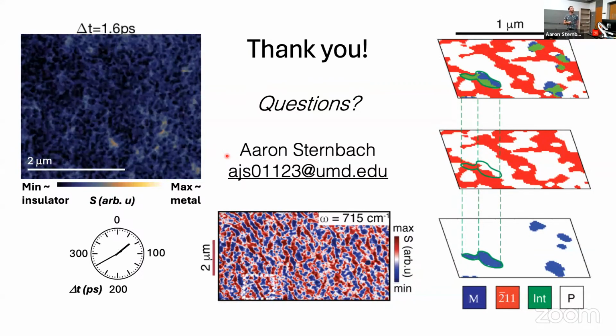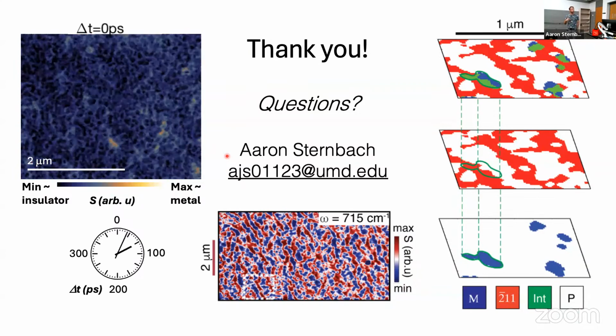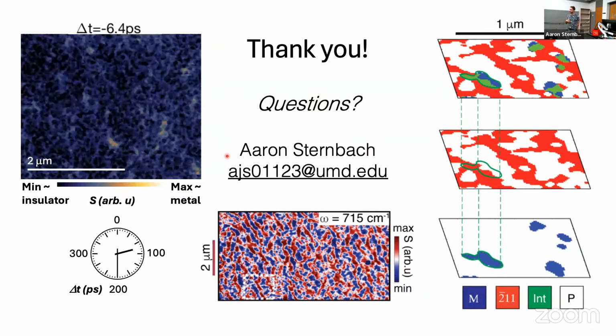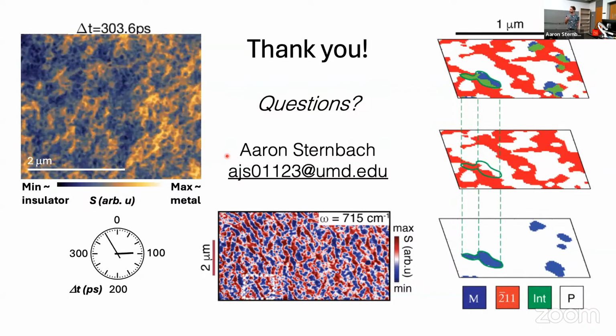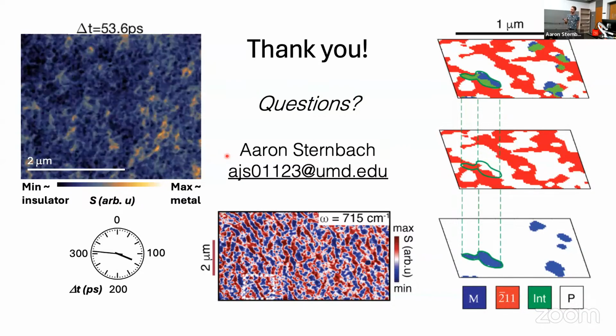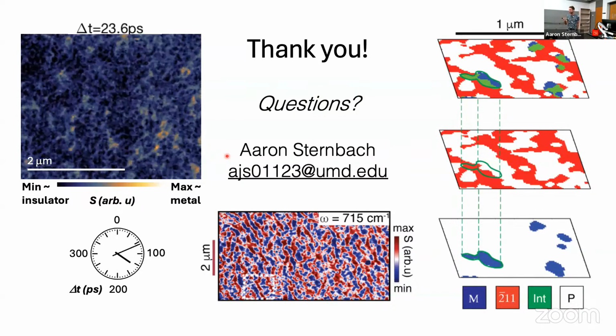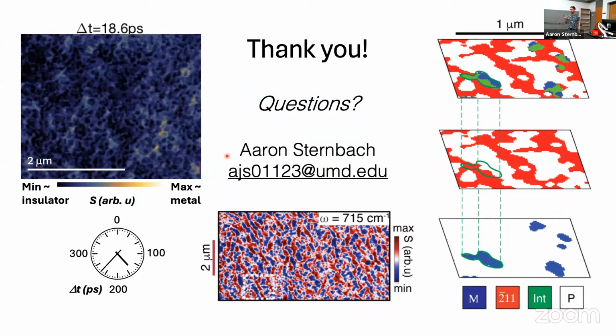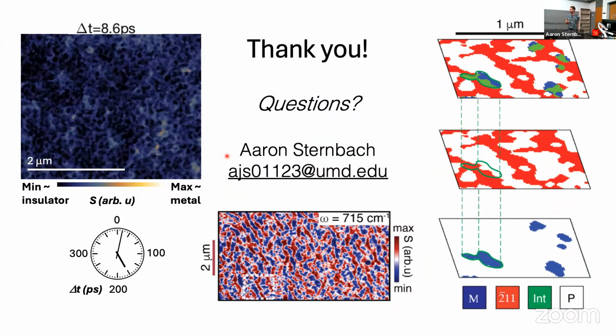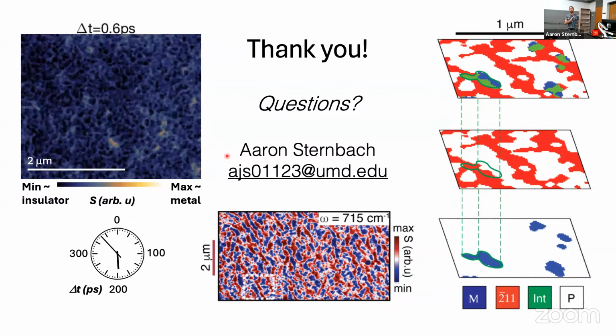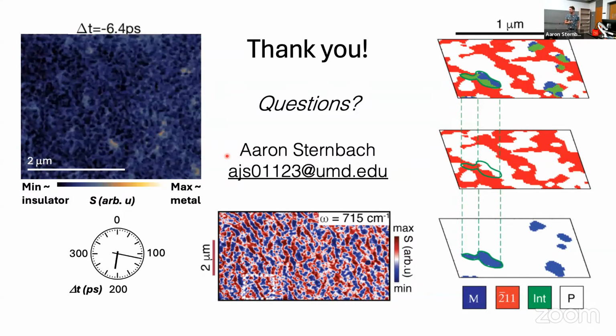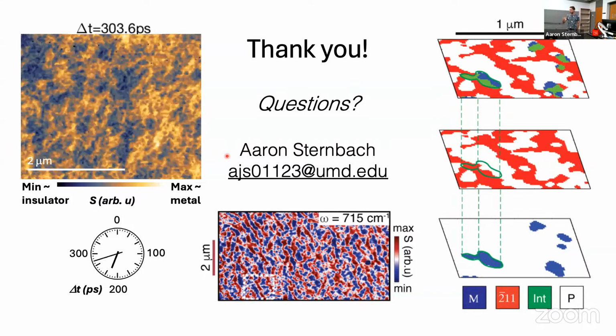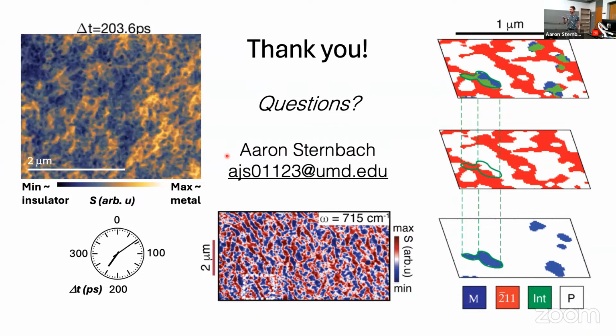And there's varying degrees of support for the notion that you can produce the electronic transition, but just at the beginning and just within tiny regions. So a small fraction of the film close to nucleation sites is believed to maybe be a true monoclinic metal. But evidence is still evolving and coming out, and there's always controversies and people arguing both points.